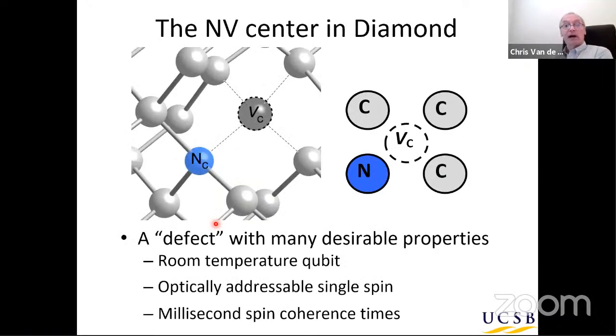So I mentioned the NV center in diamond, and quickly I want to go over that. So that's basically a missing carbon atom in a diamond crystal. And the N stands for nitrogen, a nitrogen impurity embedded in that crystal next to the vacancy. Okay, so this forms a defect. It's actually a complex with many desirable properties. It can be used as a qubit. It operates at room temperature. It gives you an optically addressable single spin, as we will see.